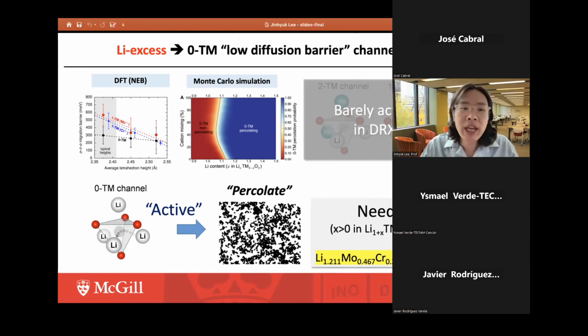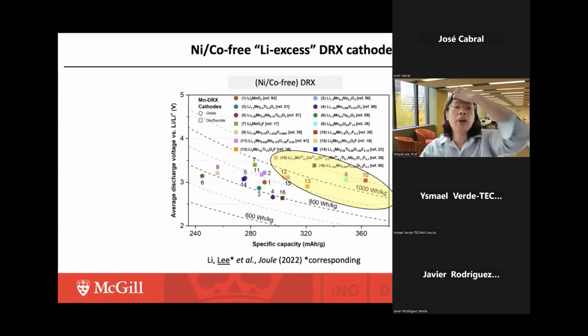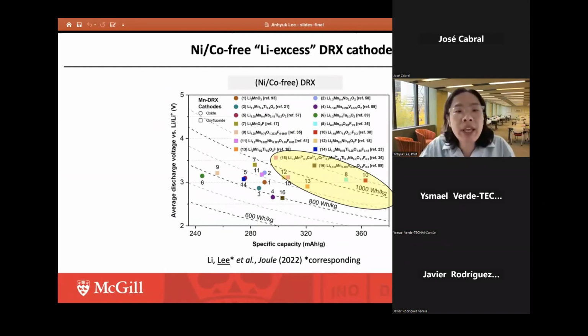So based on this simple understanding that the lithium-excess composition unlocks the lithium diffusion process in the DRX, many people in the world have started to develop various nickel- and cobalt-free lithium-excess DRX cathode materials, delivering very high specific capacity above 300, even 360 milliampere-hours per gram. And some of them start to achieve high energy density above 1,000 watt-hours per kilogram, which is a remarkably high number, considering that typical traditional cathode material stores around 700 watt-hours per kilogram.